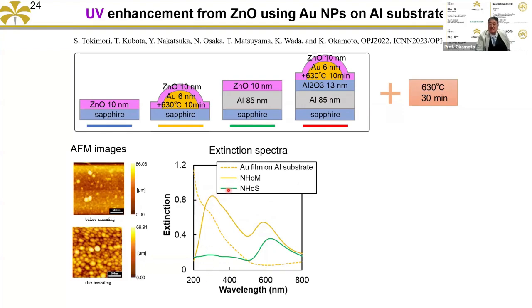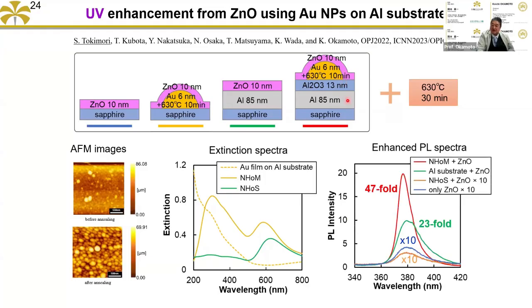It has another peak. It's a combination mode of the gold nanoparticle and also the aluminum substrate. Then we put the zinc oxide light emitter on that structure. Then we can obtain the 47-fold enhancement. Huge enhancement is available. That's why this method is very good also for the UV light region.